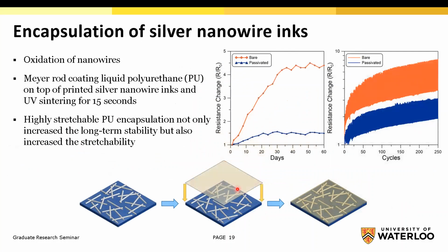Another thing is silver nanowire inks usually have an issue of oxidation. This oxidation increases the resistance with time, and it also reduces the stretchability as well. So here you can see this orange plot shows the bare, unpassivated, uncoated silver nanowire ink, and you can see at 60 days the resistance changes 4.5 times.